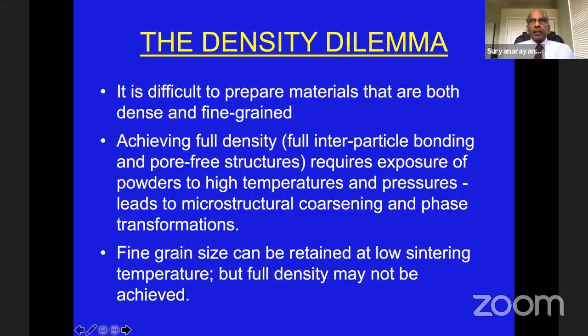But the problem is, if you want to use the densification process, it is not easy to get a material which is both dense and at the same time fine grain. Fine grain means you need very low sintering temperatures. But low sintering temperatures means bonding is not going to be good. For this, you need high temperatures. That's where there is going to be a dilemma, and that's the reason why nanocrystalline materials are better in a way.